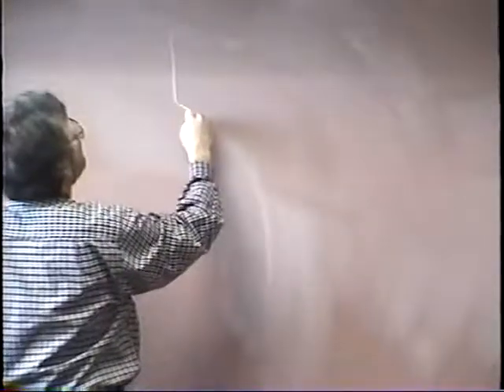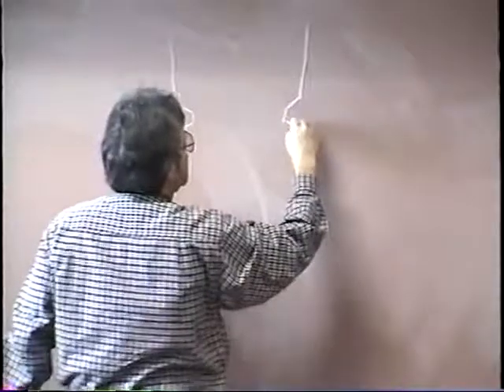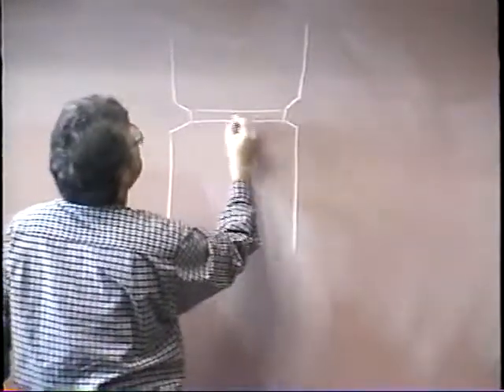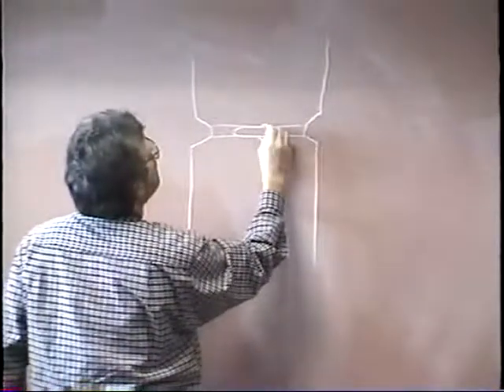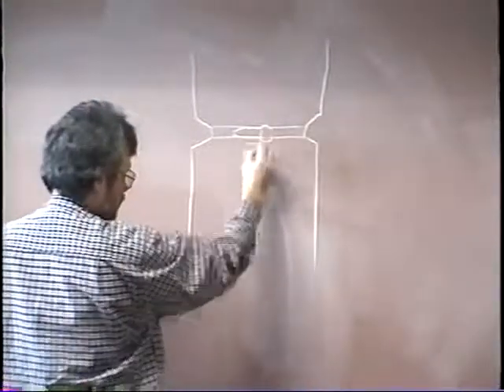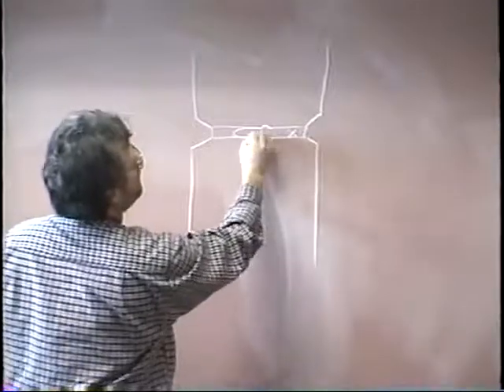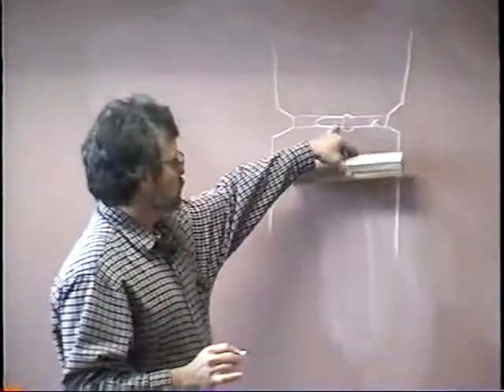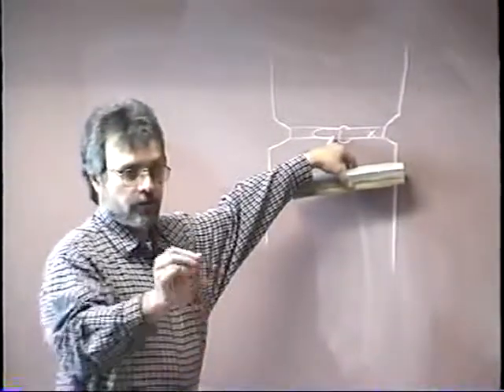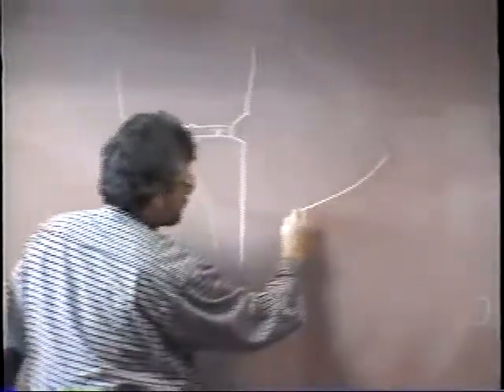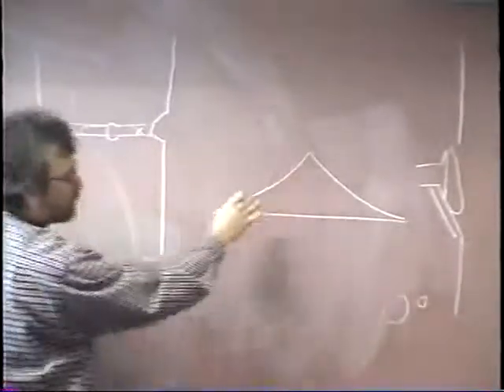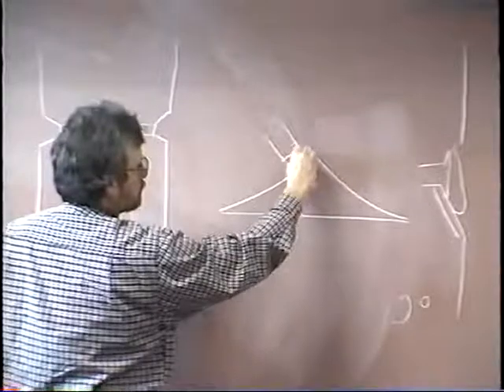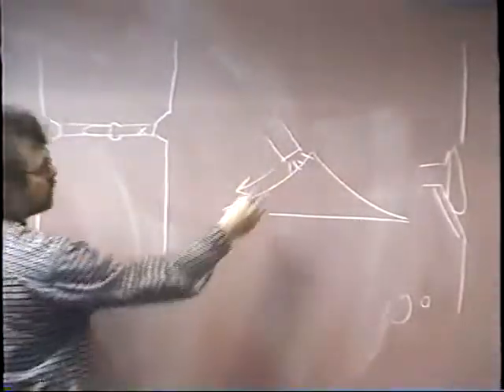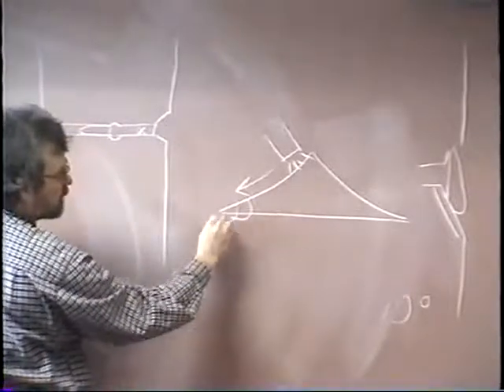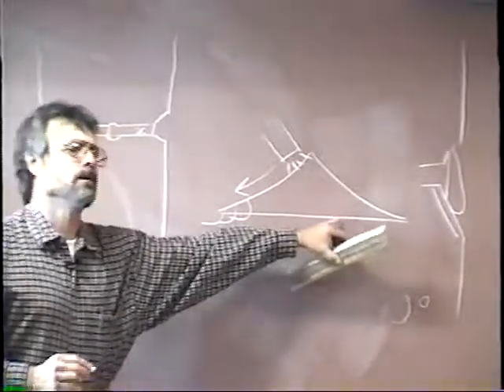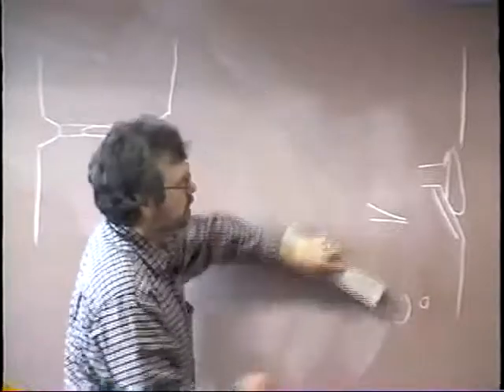When you've got your pipe, and you've got your tack in here, let's see. You've got your tack in here like so. What you're going to do is you're going to strike your arc out in here and then drop back to pick this up. But your text will go on to say that you should feather these tacks down to a fine edge, just as the way we've been showing you. And the reason for that, of course, is so that when you have your tack like this, after you've ground your tacks, you're going to start your arc back up here, and then as you progress out this way towards the end of the tack, you want that welding arc to melt through this before you reach the end of the tack so that you have a good consistent tie-in. It blends in well with that tack. We'll talk about coming into one of these tacks here in a little bit.